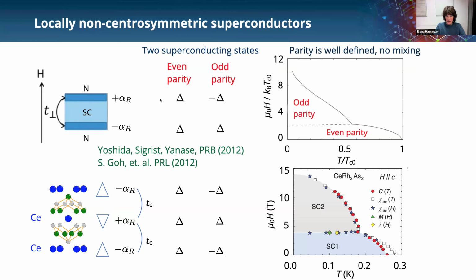And they find that then you can have two options for the superconducting state. One is the even parity state. And here parity is also well defined because overall this is also a centrosymmetric system. And for the even parity state, the superconducting gap, so here they only look at the singlet component, has the same sign on both layers. And there's also an odd parity state where the sign of the superconducting gap changes between the layers.